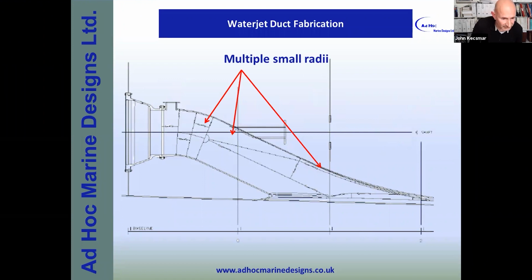This has quite serious implications when you're fabricating structures like water jet ducts. Because as you can see here, there are multiple small radii. So extreme care and attention must be paid to the rolling and the forming of the plating when making the jet duct. And it also implies really you should use O-temper.